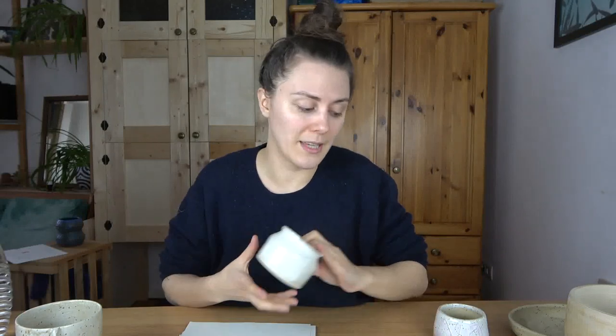It also causes s-cracks, which we'll talk about later. Make sure everything is drying evenly. This also happens when the glaze is just too thick on the bottom — the glaze is transforming and shrinking and puts way too much stress on the clay. If you pour glaze in and then wait five minutes before you pour it out, the glaze is going to be too thick on the bottom and you can get a crack like this.